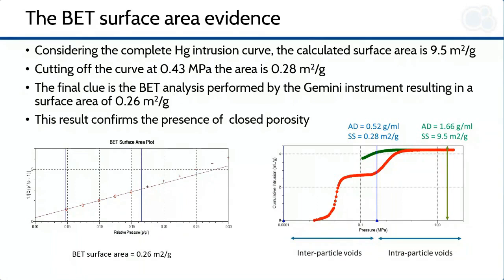Mercury porosimetry gives about 9.5 square meter per gram using all the data up to 414 megapascal. The BET surface area on the instant coffee gives 0.26 square meter per gram, that is much less. In physisorption we use nitrogen at very low temperature, thus the possible diffusion of nitrogen into the closed voids is completely disadvantaged. Therefore, physisorption measures only the external surface due to the granule's roughness. If we calculate the surface area at the cutoff pressure that we have identified before in the mercury intrusion curve, we get an area of 0.28 square meter per gram, also by mercury porosimetry. This is another proof of the inaccessible void's presence.